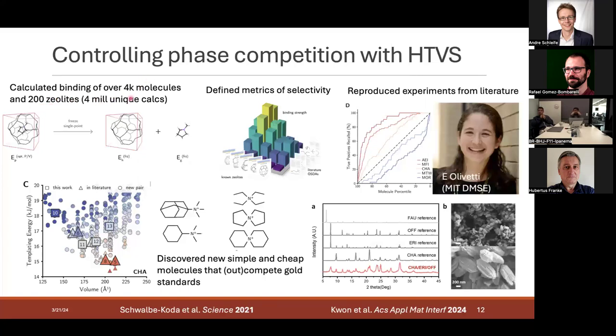And we literally went and did the full matrix of how all these molecules fit into all these zeolites. And a bunch of them don't fit because the pores are smaller than the molecule. That's why this number is not the product of these two numbers, right? Because, and then we try different random configurations to make sure that we explore how these molecules fit. So we end up with this very large matrix of not just affinity, this molecule fits well with this pore, but also selectivity. So not only is this molecule and this zeolite a good pair, but there is no better pair out there, right? There's nothing the molecule would rather do than fit this pore.